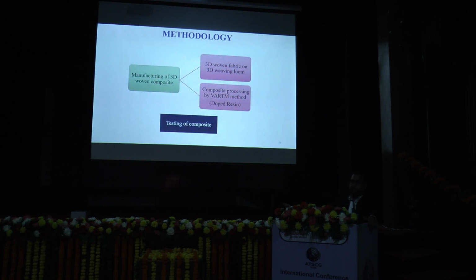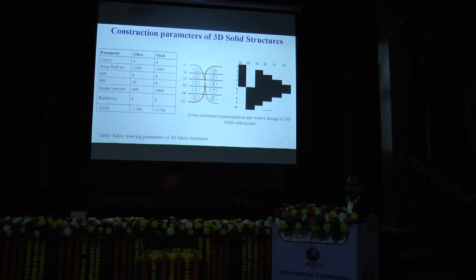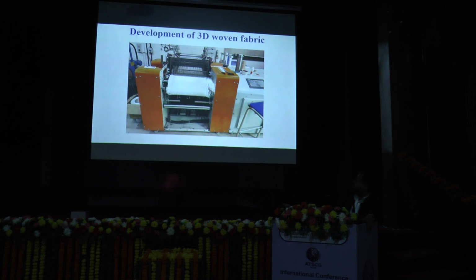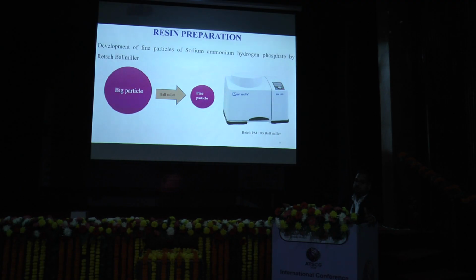This is our methodology. First we develop the 3D woven fabric and the 3D woven composite with resin processing by the VARTM method. Then comes testing of the composite. This is a construction parameter of our 3D composite structure. Here we have developed the glass 3D woven fabric, and in the resin preparation, we first use sodium ammonium hydrogen phosphate. First we heat sodium phosphate at 120 degrees for 4 to 5 hours. After that, because it is very hygroscopic, we convert it into fine particles by a nano ball milling machine.